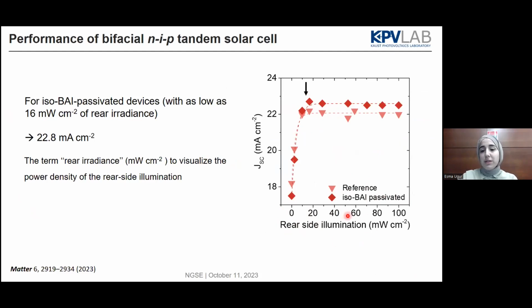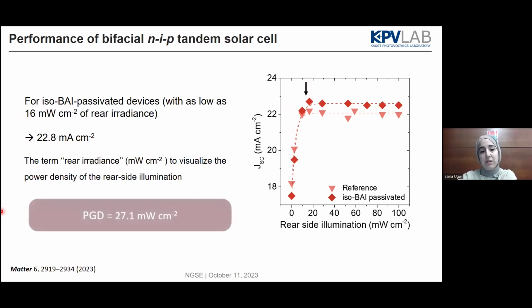With the different rear side illumination, as I mentioned previously, by changing the filter you can mimic the reflected light, because different backgrounds give different rear side illumination to your device. We have a quite nice sharp increase at the beginning. With a rear illumination as low as 16 mW cm^-2, you can reach close to 23 milliamp per centimeter square for these devices. That gives a power generation density of more than 27 milliwatt per centimeter square. This is not only helping with the performance, but also what we are expecting from these 2D perovskites is that the samples will be more humidity resilient.